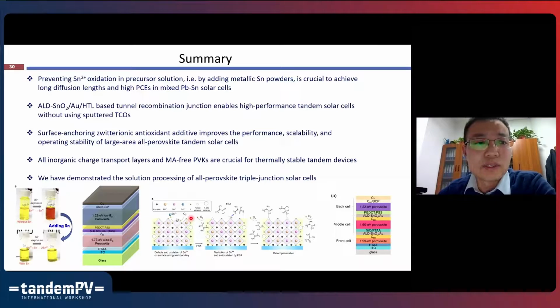We also developed a tunnel recombination junction that enables us to get high performance tandem devices without the use of the sputtered ITO layer. We also developed another strategy to improve the performance, uniformity and operating stability of larger area all-perovskite tandem devices, by adding a surface-anchoring, zwitterionic antioxidant additive in the precursor solution. And we also show that by using all inorganic charge transport layers and MA-free perovskite materials, we can get quite thermally stable tandem devices.